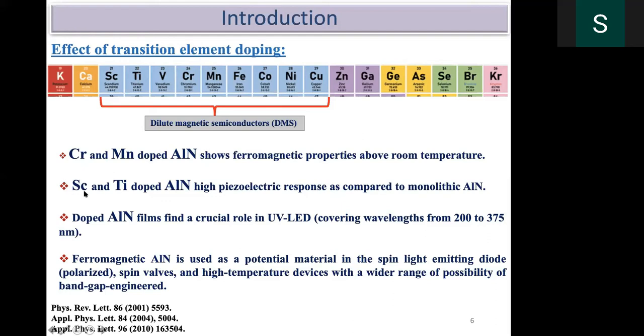And if you dope scandium or titanium, basically it will increase the anisotropic nature, and it can be used as a piezoelectric material. The reason is the potential stored in the system is much higher compared to the chromium and Mn doped aluminum nitride.